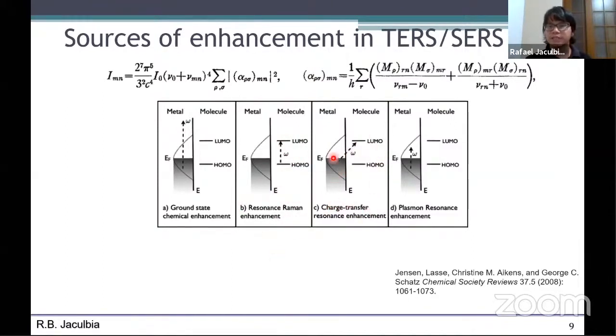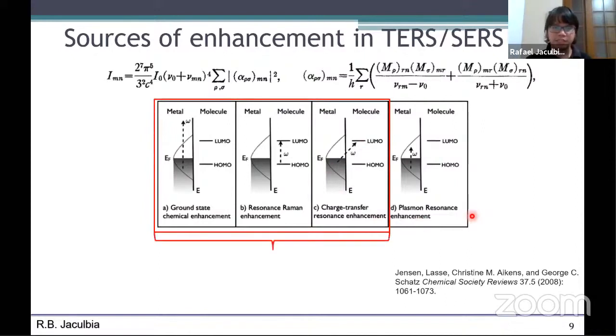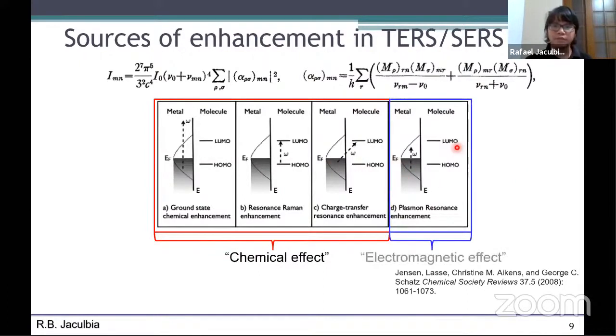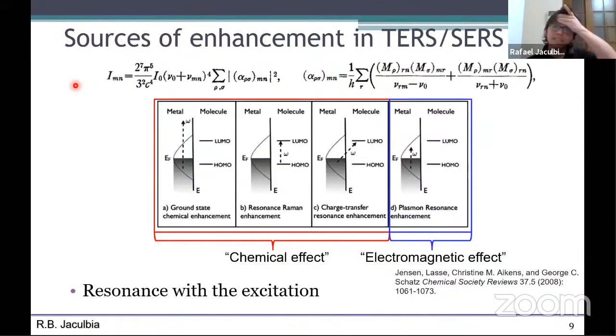And as I said before, charge transfer resonance is when the energy of the incident light is equal to this energy. So you have the so-called charge transfer resonance, and this is the so-called chemical effect. And the other one is the plasmon resonance effect, where your metal has a certain plasmon resonance, and the excitation is in resonance with that plasmon energy, and then you can get another enhanced signal. So in general, the enhancement in TERS is defined by basically the resonance, or how far your mode is from the energy of your laser or your excitation light.